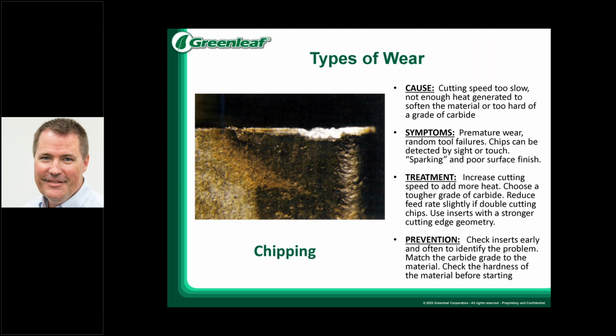If you can see, for treatment of this type of wear, you'd be wanting to look at a tougher grade of carbide. Anything you can do to help reduce double cutting of chips as well, whether you may have to change into a different cutting chip form, or increasing your feed rate to thicken up the chip in order to have it evacuate quicker.